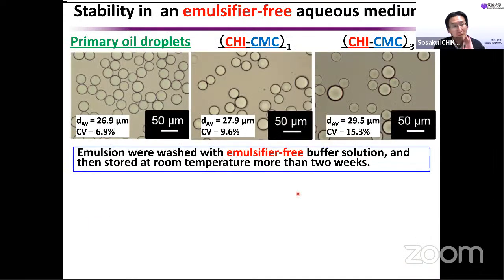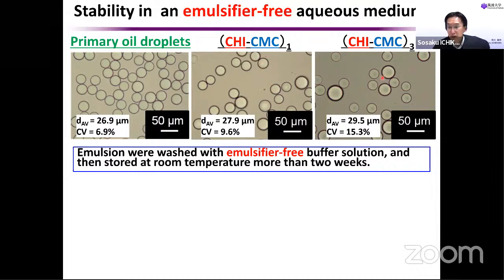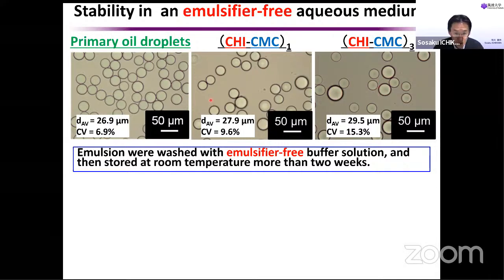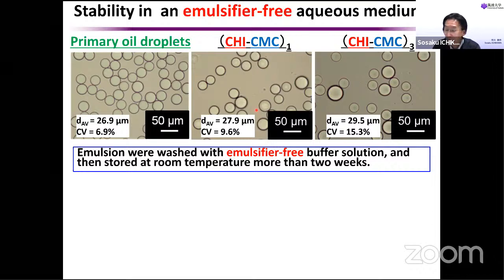One example of the stability enhancement by coating is shown in this slide. This is the primary oil droplet. This is a chitosan and CMC coating. This is a six-layer coating of the oil droplet. Then we wash out the emulsifier in the aqueous phase. Let's see after the removal of the emulsifier.